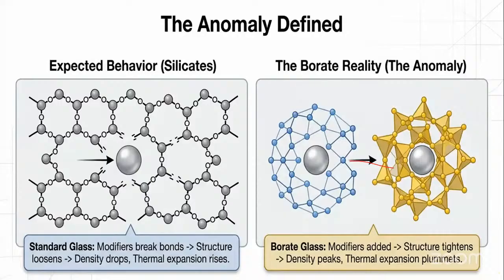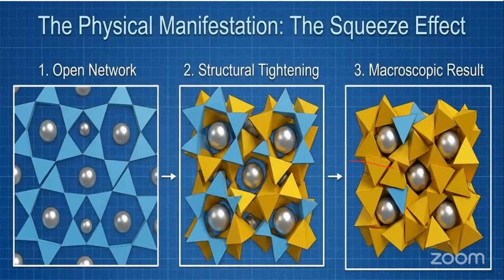But when you look at the borates, there was something which happened in a different manner. Up to a certain concentration, it followed the behavior that you see with silicates. But beyond that concentration, the structure started tightening, the density increased, and the thermal expansion started falling down. So this led to formation of strong BO4 regions, and again after 33%, it loosens its structure, density falls, and that is where it leads to an anomalous behavior, which we call the boron oxide anomaly. So normally what happens here is it is undergoing that squeezing effect, and because of the structural tightening, they undergo this anomaly.